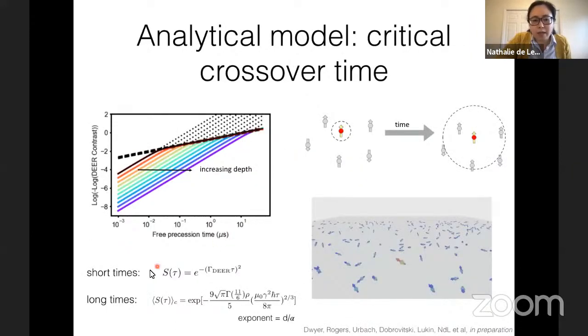Then we can write down an analytical model for what these exponents should be. It's not easy to solve analytically, but we can solve it in a couple of limits. At very short times, we recover e to the minus gamma tau squared, and at very long times, we get this exponent of 2/3. Instead of some random exponent in between, what we see is that as a function of time, there is a critical crossover between the n equals 2 and n equals 2/3 limits. This is a simulation plotted on a log plot, which is not that easy to think about, but it gives you a nice visual cue that the slope of this curve is the exponent of the coherence decay. So you can see that you go from n equals 2 to n equals 2/3.